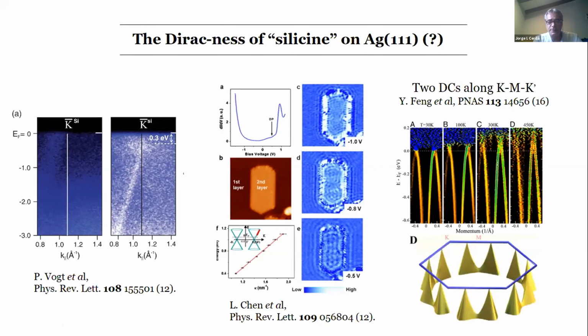Still, recently there was a paper where they showed that, well, maybe there are no Dirac cones at the K points, but they claimed they were seeing Dirac cones at the M, along the K-M direction, and actually even two of them, by symmetry. We see here they raised the temperature so they could occupy the states above the Fermi level, and they could actually derive these Dirac cones. So we try to address this point here, because it had not been addressed from the theoretical point of view.